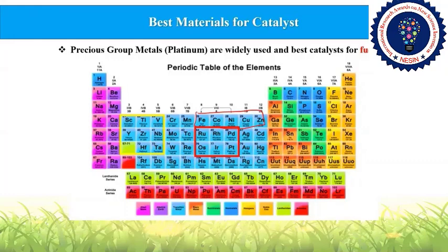Alternatively, we are investigating intermetallic nanoparticles of platinum with early D-block metals. The enthalpy of formation is very high, which is important for stability. However, synthesis is very difficult because these metals are oxyphilic. Throughout the synthesis, we need to maintain strict inert conditions — everything must happen under an argon atmosphere — otherwise oxides such as TiO₂ and vanadium oxide will form.